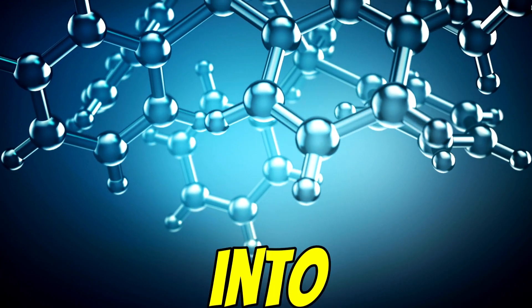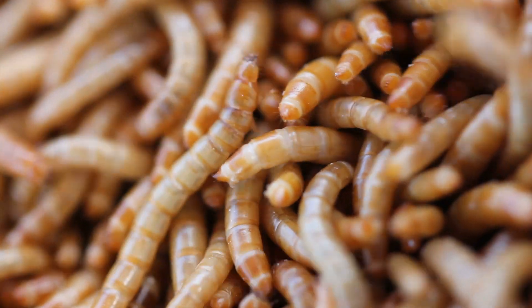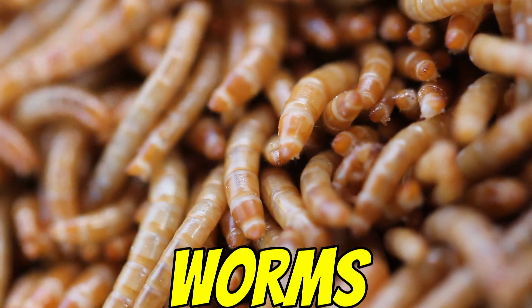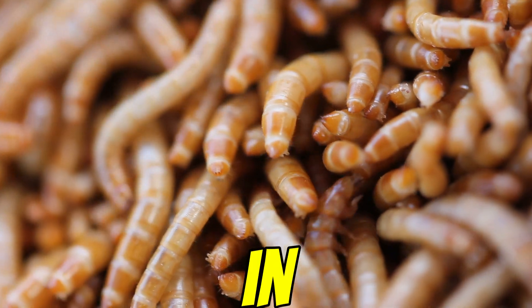They break the chains into smaller bits — molecules that contain oxygen, including something called ethylene glycol. And they quantified this. The study found that 100 wax worms could break down about 92 milligrams of polyethylene in just 12 hours.